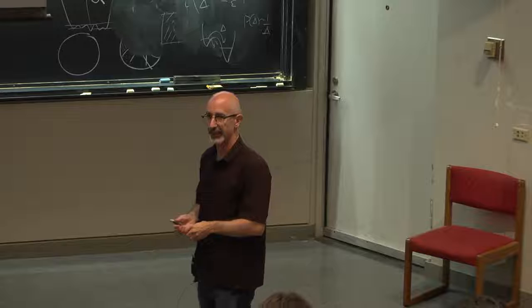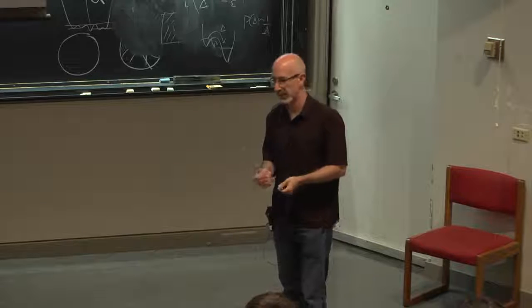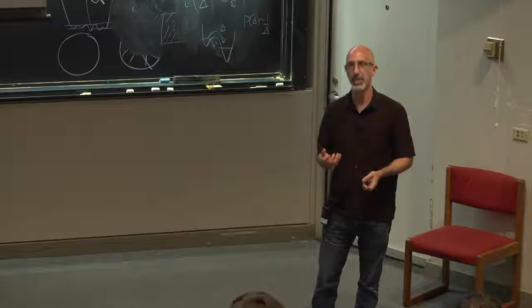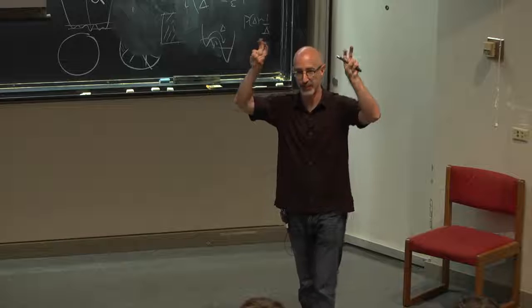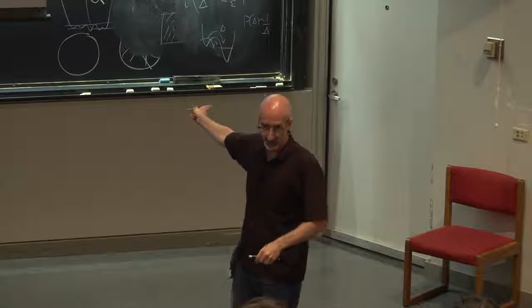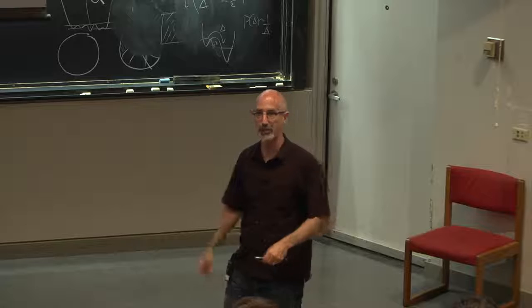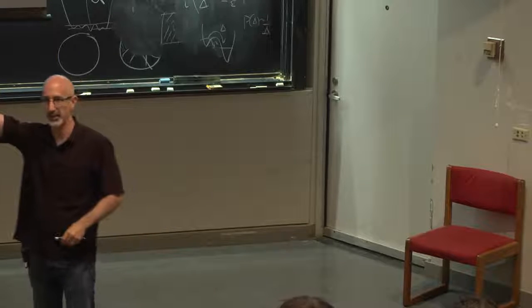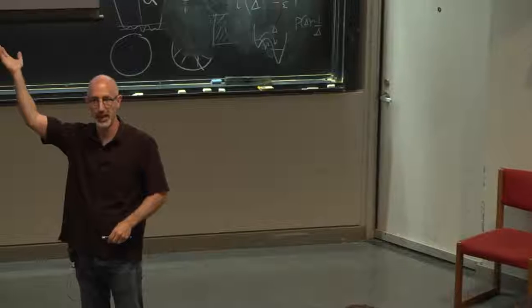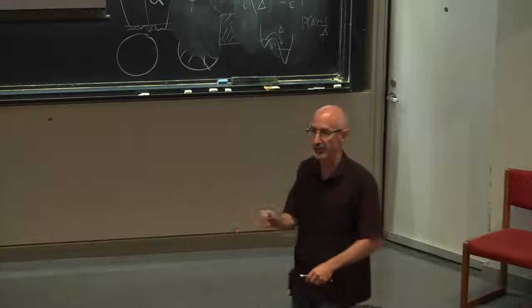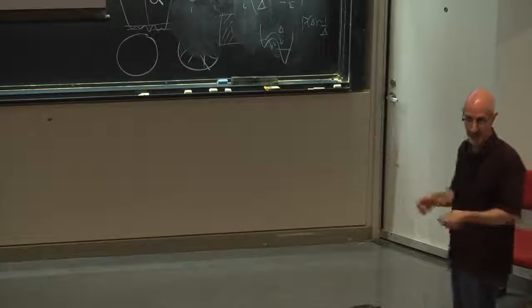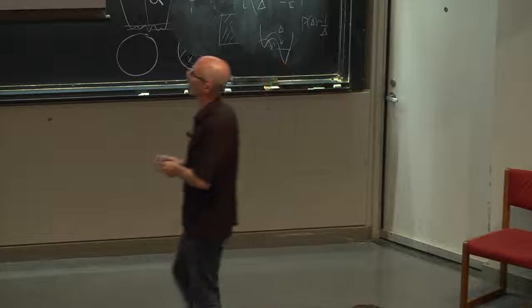There are also very interesting connections with the glass transition. So it's been known for a very long time that in some sense there seem to be correlations between what you would expect for the amount, let's say, of dynamical heterogeneity that's frozen in at the glass transition and the density of two-level systems. So one speculation you could make is that the two-level systems are the remnants of the dynamical heterogeneity that we talked about. And they're just the little pieces that are left of these clusters that can't move through the system anymore. They can just move back and forth locally. That's entirely plausible. I'll show you a picture in a second that makes this connection ever so slightly more tangible.